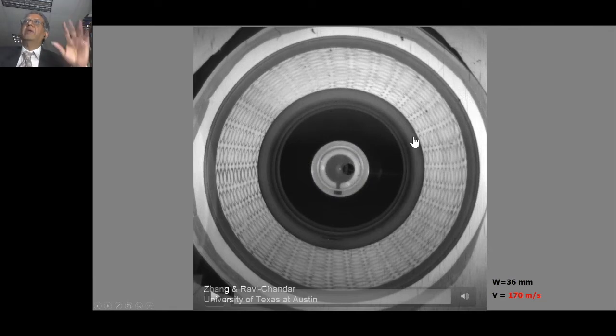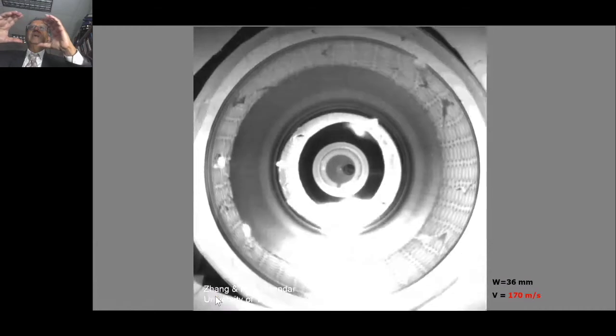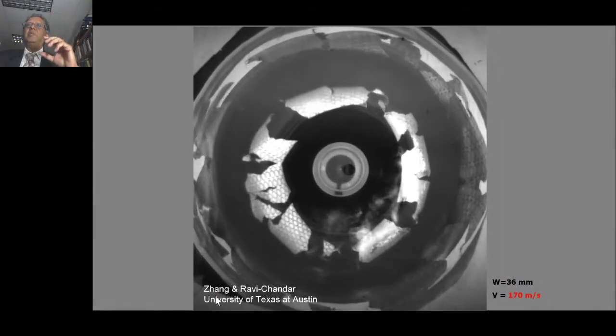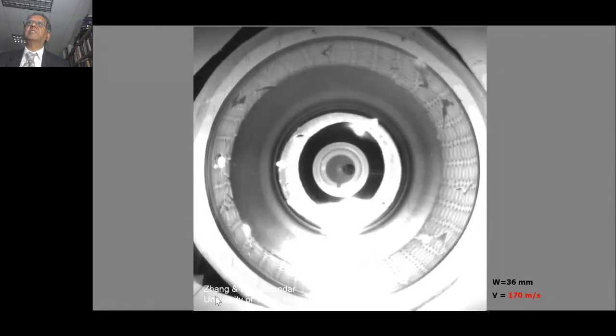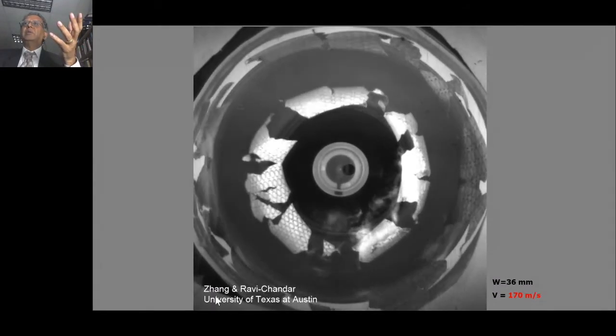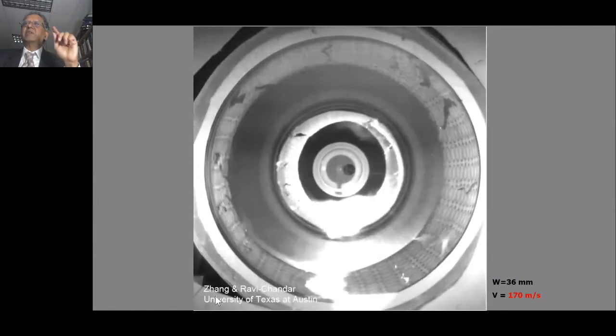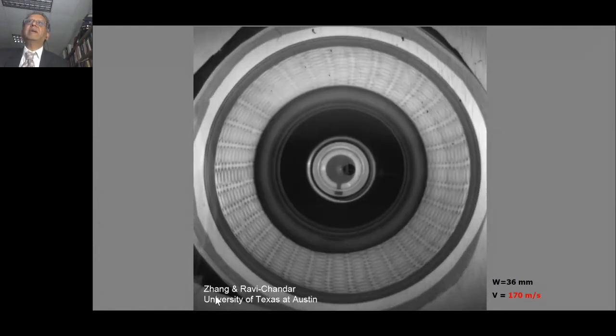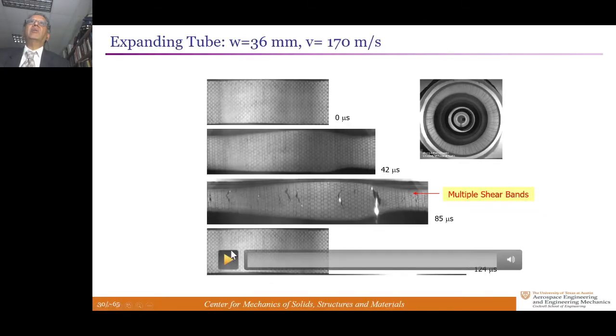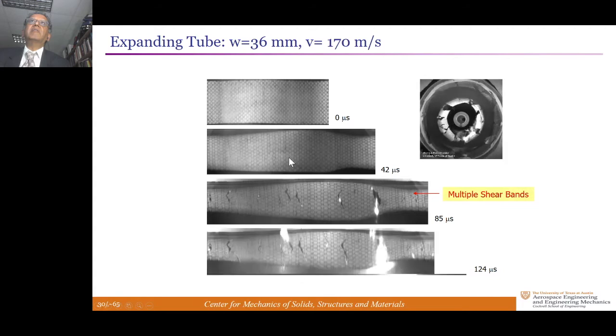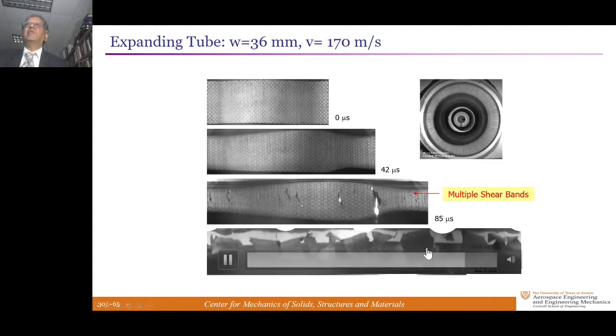This is now a different high-speed camera, lower spatial resolution, but much easier to use. On the surface of the conical mirror, you see the surface of the cylinder. The cylinder was etched with a pattern of circles to be able to measure strains post-mortem. And I'll play this video, and you can see the cylinder expands out. At some point, it fractures into multiple pieces, and you can see the sparks flying from the arc discharge. This is a deceptively slowed down experiment. The entire experiment took about 80 microseconds, but you can slow down everything with digital magic. All right, so you can then look at every frame, and you could see the onset of localization, the onset of fractures, and how the fragments form, and so on.